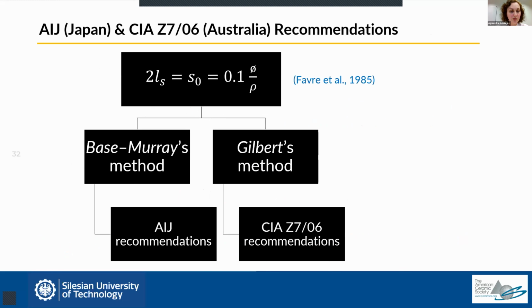And what is important, because I don't want to go into too much detail, what is important in these approaches, in contrast to, for example, the European approach, is that this approach doesn't assume that we have a stabilized cracking pattern. On the contrary, when we know the value of the expected imposed deformation, we calculate the expected spacing of the cracks, and we compare it with the expected stabilized cracking. This way we know in which state we are, and we calculate the expected crack width accordingly, because it is important to remember that the slip length changes with the value of slip, which means the value of the load, and these methods take this into consideration.